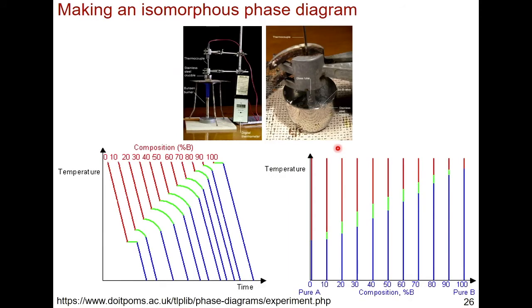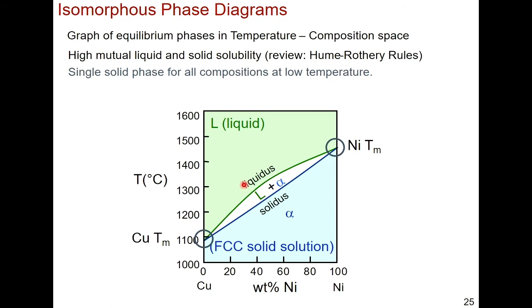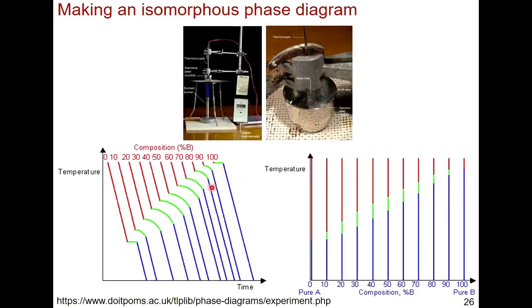Okay, so actually before I get to the tie line, how do you measure this? You can actually measure the temperature. You can reproduce this phase diagram by melting together copper and nickel and just measuring the temperature over time. And then if you plot the composition, temperature as a function of composition, you can map out that area that we saw in white in green right here. Okay, so you can just put it in a pot, control the temperature and the environment, and you can track this and make the phase diagram. And that's what people used to do, is this is how we know all of this information. There was an entire group of people who like very carefully did all of these measurements, okay?